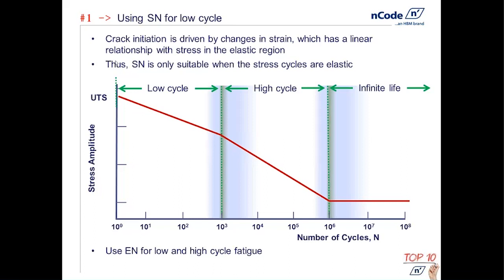So if you find yourself in a scenario where you have plasticity occurring in hot spots or you see failures occurring in the low cycle counts, the best approach for crack initiation is going to be to use the strain-life methodology. This is an approach that is applicable for both low and high cycle situations.